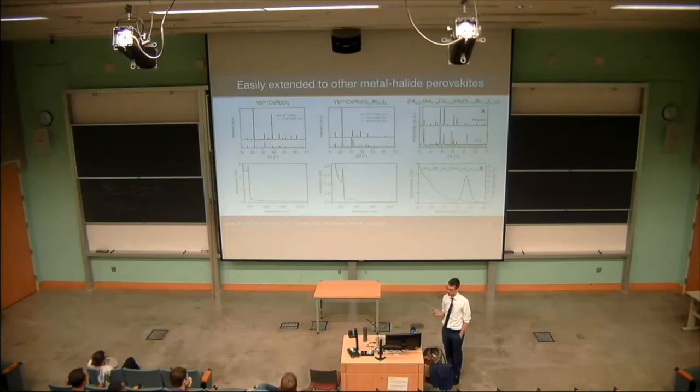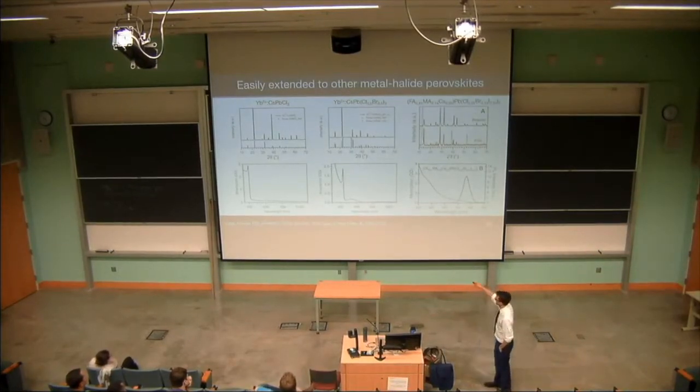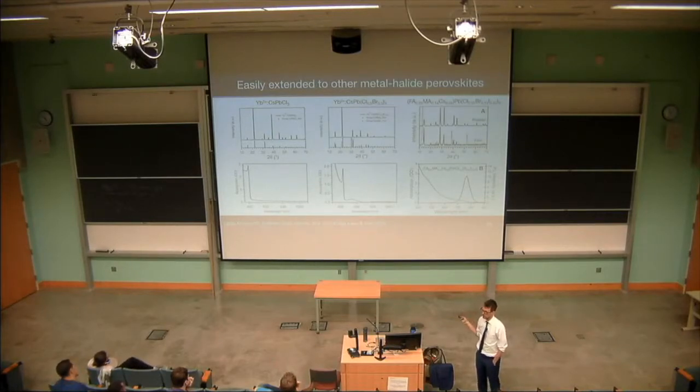And this isn't just limited to this ytterbium-doped cesium lead chloride. This works with the chloride. We find this also works with a mixture of the chloride bromide. So now, astoundingly, just putting these in an evaporating source and heating this up either slowly or rapidly, we can form apparently incredibly transmissive and ytterbium-doped films.